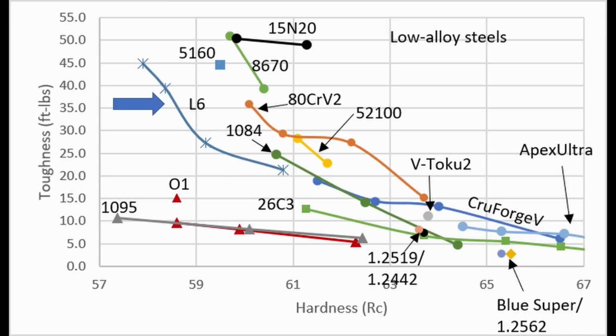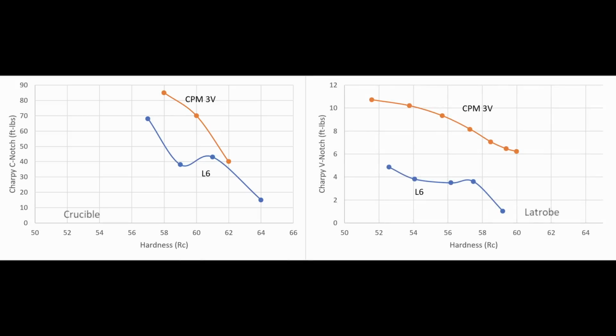And some knife makers were disappointed in this or questioning the result. L6 is a nickel steel. Why isn't it up in the 40, 50 foot-pound range? And one thing I said in response is that some of the steel companies also don't rate the toughness of L6 as being all that high. So I have data from both Crucible and Latrobe with different toughness tests than I use.